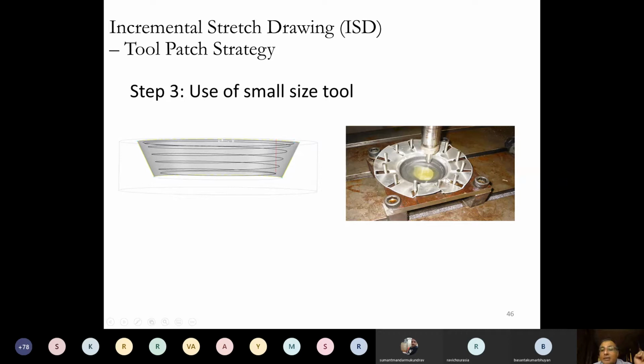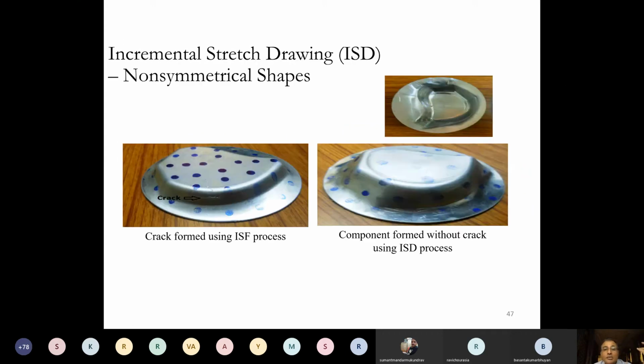Later on we cut this on this side, and our desired geometry was obtained, which was much better than the conventional processes. We have a comparative analysis also, so we could generate non-symmetrical shapes with this. When we were using the conventional ISF process, you can see the crack formed at a very small depth. But when we used the ISD process, components were formed without crack, and up to a very large depth.